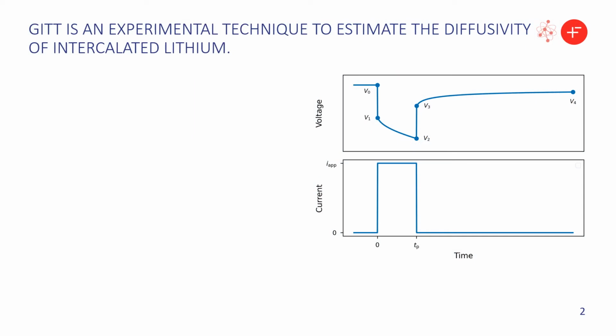One of the most common ways to estimate the diffusivity of intercalated lithium is using this GITT, or galvanostatic intermittent titration technique, which consists of applying a constant current pulse to the battery and then switching it off and letting the battery reach equilibrium again. And this pulse needs to be short and weak, so it causes small variation in the concentration, in the state of charge of the battery. So we need to repeat it many, many times to sweep the whole range of operation that we're interested in.